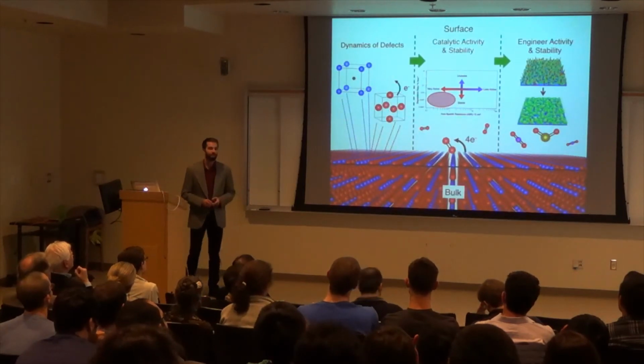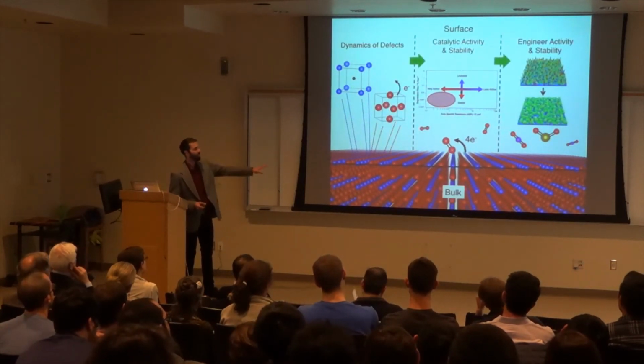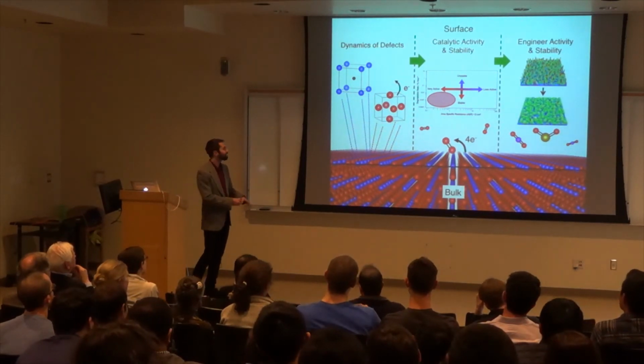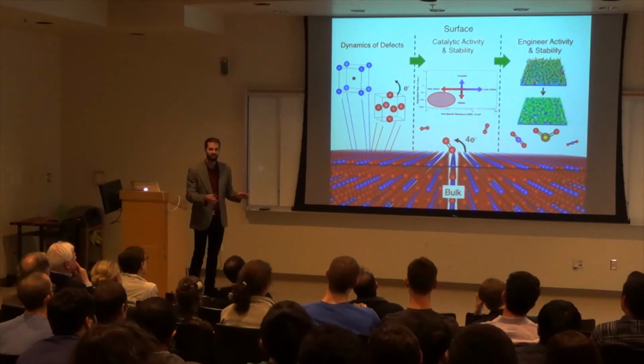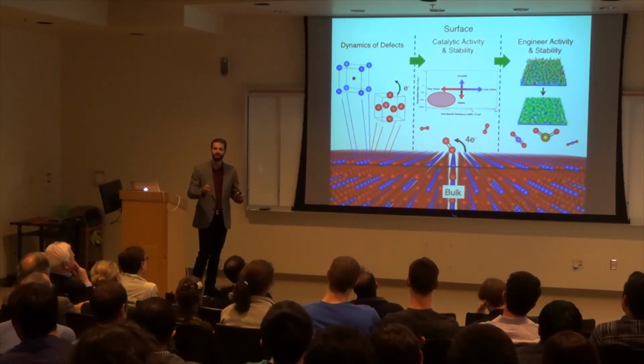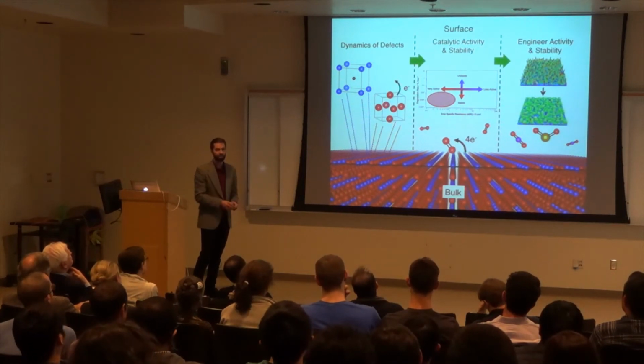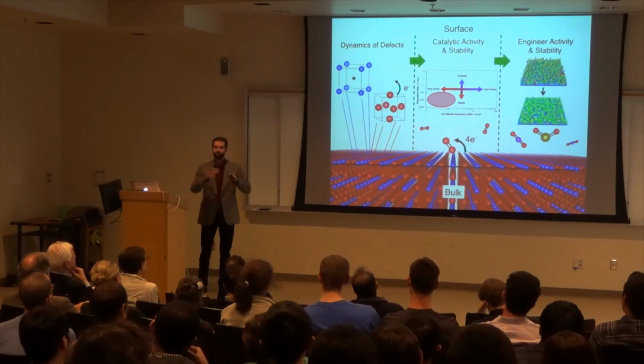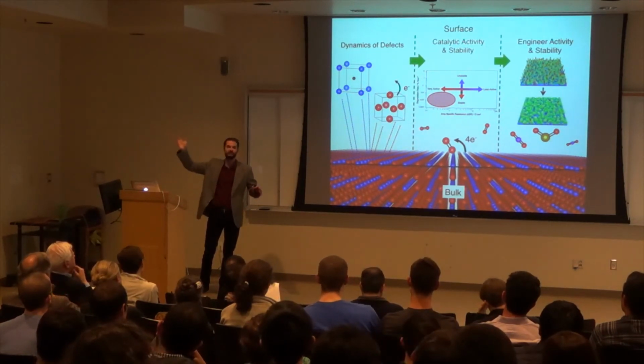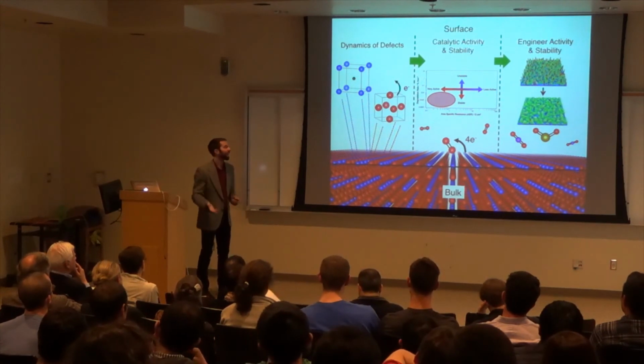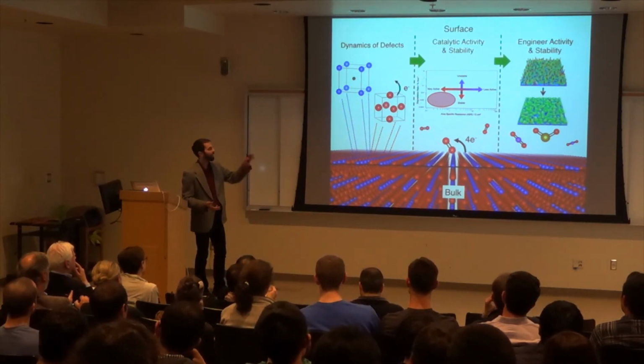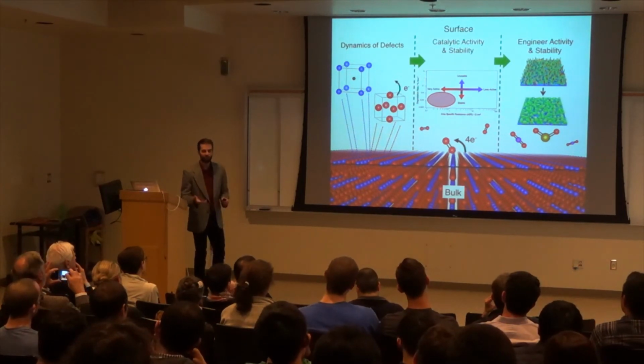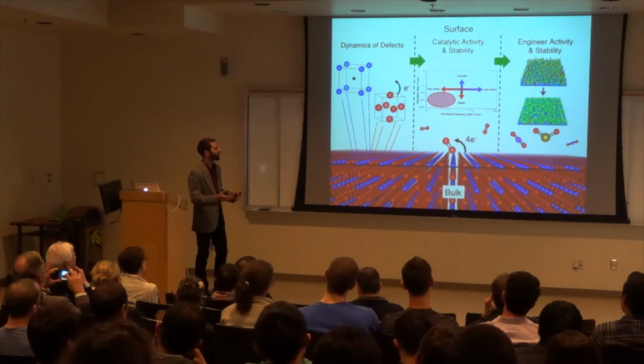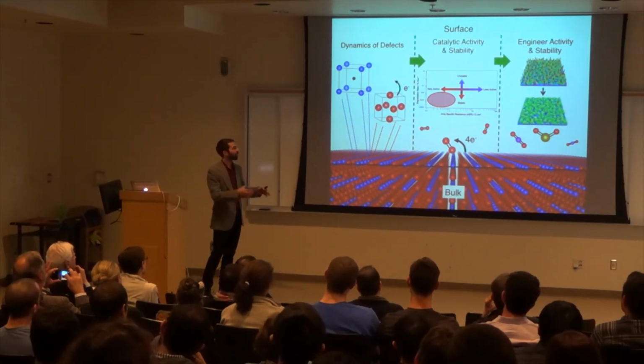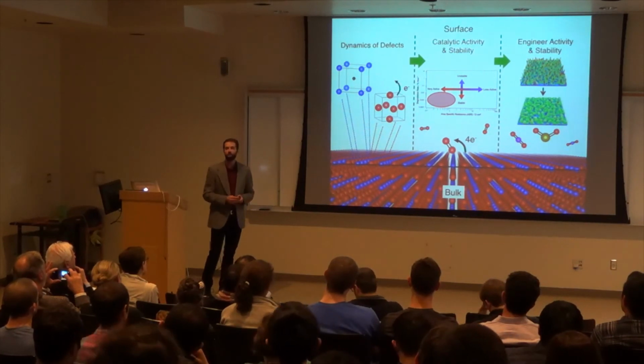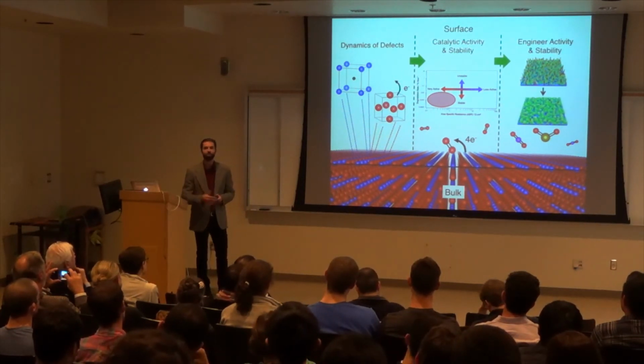So, to summarize the talk today, I've taken you on a journey where I've discussed how the bulk cations can influence what you see at the surface. And based on what we identified at the surface, we then moved to correlate the surface to catalytic activity and stability of these surfaces. Based on what we learned from how these surfaces react in a very clean environment and those in an environment where we have gases that can poison the surface, such as sulfur oxides and carbon monoxide, we then figured out a way to engineer the surface to be stable under relevant operating conditions. So in a sense, we've completed the materials science loop. We've used fundamental science to inform the engineering of our surfaces for improved performance.